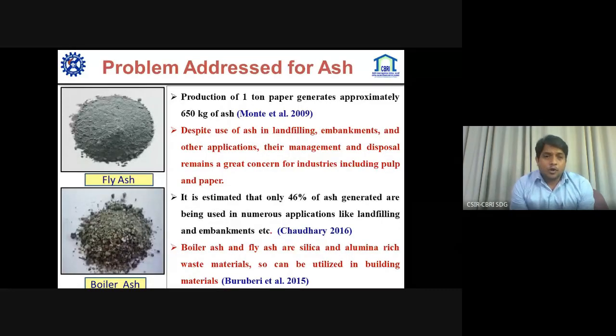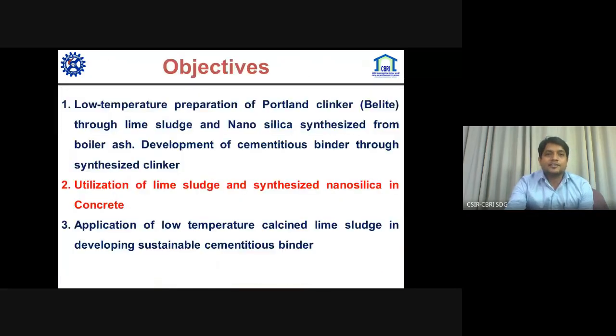The problem being addressed with paper industry's fly ash and boiler ash is that production of 1 ton of paper generates approximately 650 kg of ash. Despite the use of ash in landfilling, embankment, and other applications, some issues remain a great concern for paper industries. It is estimated that only 46% of ash generated is used in numerous applications. Boiler ash and fly ash are silica and alumina rich materials, so they can be utilized in building material applications.